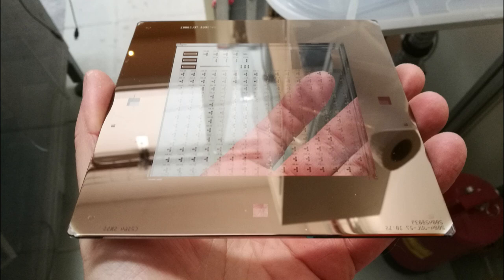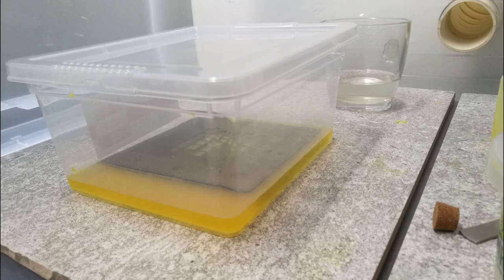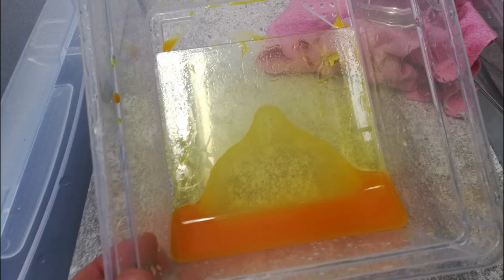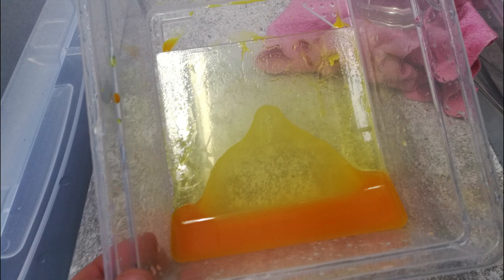The etchant is now ready for use and will etch 100nm layers of chromium in a matter of minutes at room temperature. After finishing, remove the quartz plate and put it into clear water to rinse it and remove the acid solution.